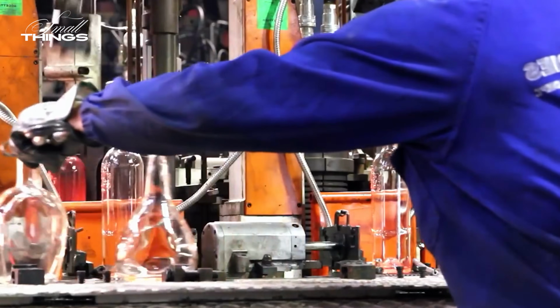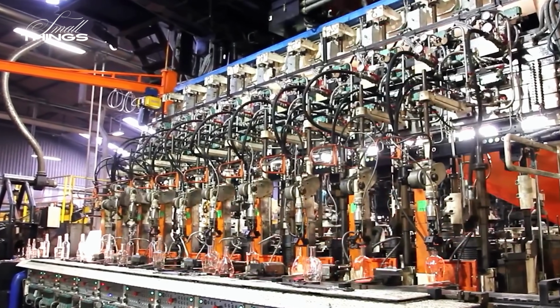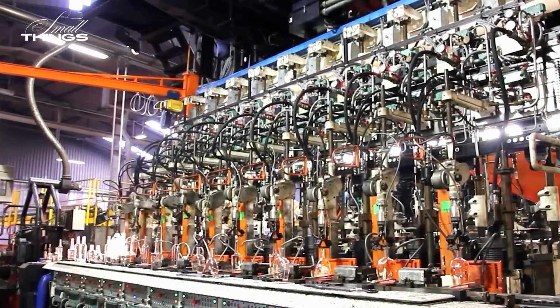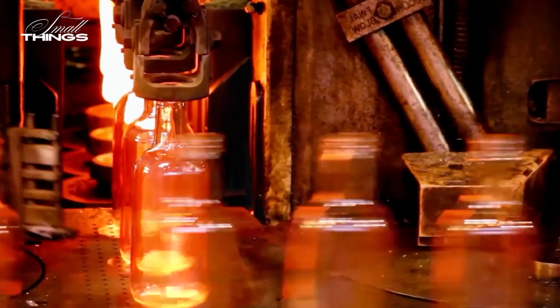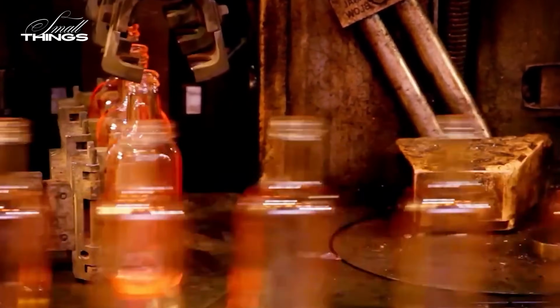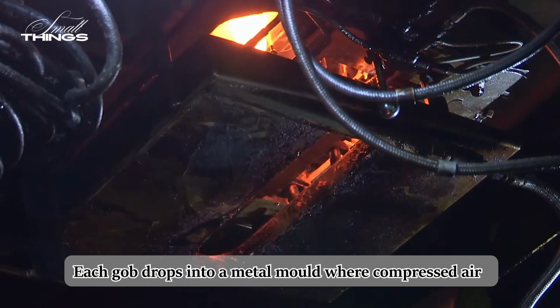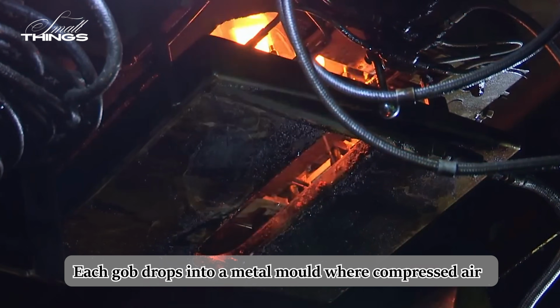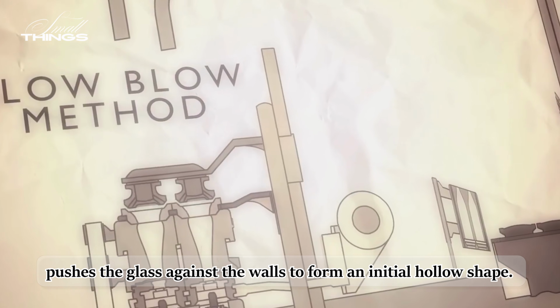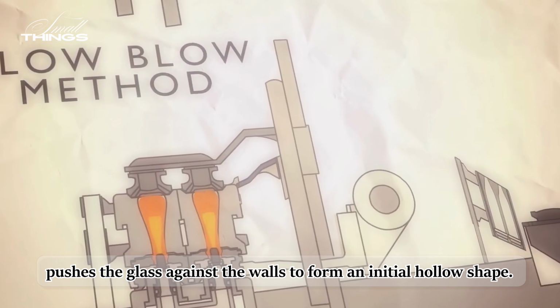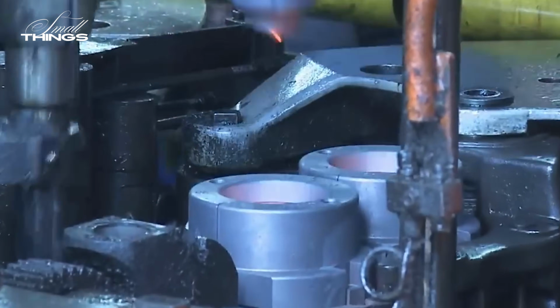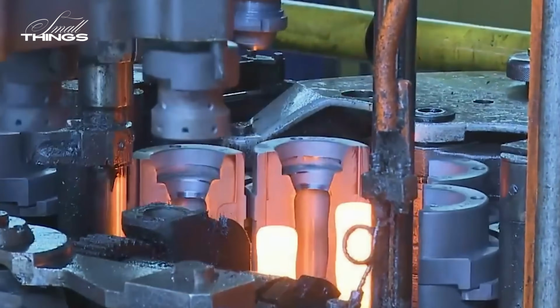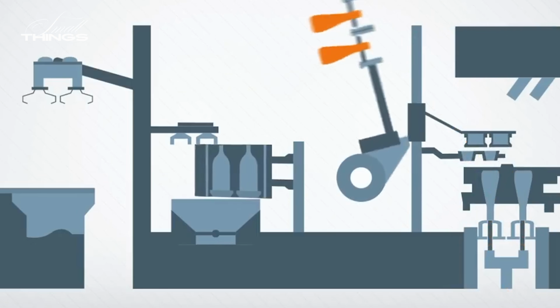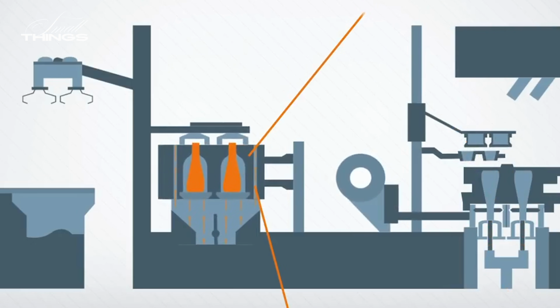For bottles, the molten glass is drawn out in a stream and cut into measured portions called gobs, each at around 1,100 degrees. Each gob drops into a metal mold where compressed air pushes the glass against the walls to form an initial hollow shape. The bottle moves to a second mold where another air burst expands it to its final dimensions. The shaping sequence takes less than 2 seconds.